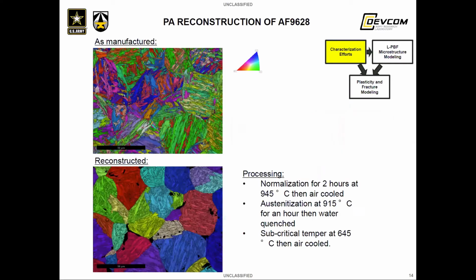So some prior austenite reconstructions are harder than others, depending on the processing of the martensitic steels being studied. Here, a sample of wrought and heat-treated AF9628 is shown with the heat treatment shown on the right. This sample was austenitized and quenched, showing a clean martensitic structure in the top image. The reconstructed austenite grains are shown in the bottom image, exhibiting some twinning, such as the grain, for example, at the very top right of that reconstructed image. This sample can be compared to the next sample on the next slide, which is a bit different.